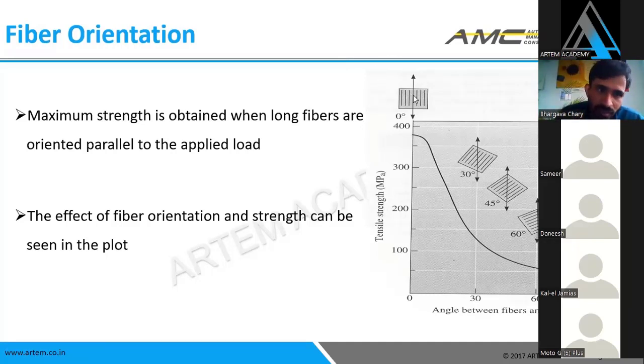Here the long fibers are oriented parallel to the applied load. So we have to use the fibers more intelligently, so that fibers are always placed parallel to the loads. So here this is an orientation. If we make a 45 degrees plate, all the fibers are at 45 degrees, 60 degrees. So when we make a mechanical test and orient the fibers parallel to the loads, it has more strength compared to the horizontal loads.